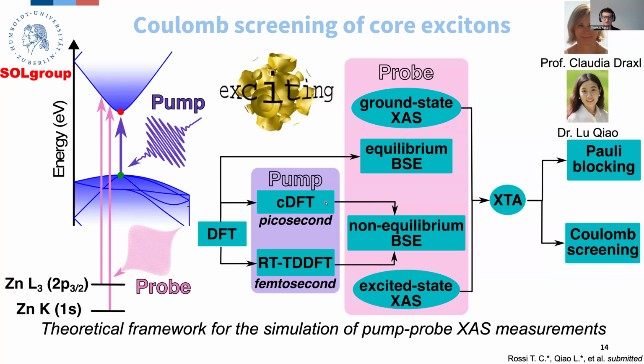And once you have the electronic structure of this excited state, you can run a Bethe-Salpeter equation on top of it that delivers the excited state X-ray absorption spectrum. And now you have all the tools that you need to be able to reproduce the experimental data, because the pump probe is simply the difference between the excited state and the ground state that delivers what we call the X-ray transient absorption. So it's the pump probe difference spectrum, essentially.